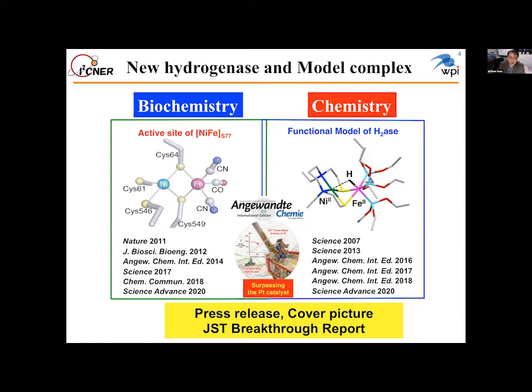In my case, I also developed the finding of new enzymes, particularly very interesting enzymes. For example, in most cases the hydrogen activation enzyme, which we call hydrogenase, is very sensitive to oxygen, but we found some enzyme that can activate hydrogen even in the presence of oxygen. Also, we made a fuel cell with our developed enzyme, whose ability is better than the Pt catalyst.